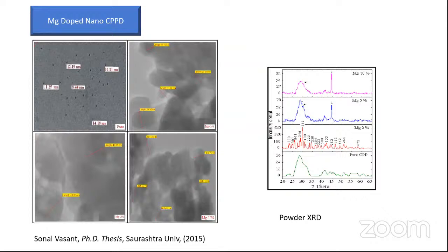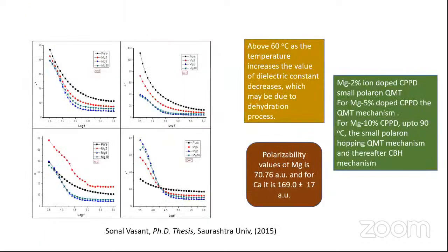These are the pictures of magnesium doped CPPD, and on the right-hand side, the powder X-ray diffractogram. And again, these show the variation of dielectric constant at different frequencies. For 2% magnesium ion doped CPPD, the small polaron and quantum mechanical tunneling mechanism. For 5% magnesium doped CPPD, the quantum mechanical tunneling mechanism. At 10% magnesium doped CPPD, the tunneling mechanism, and thereafter the CBH mechanism is developed. So they depend upon the concentration and also on the temperature. So this mechanism changes with different types of doping as well as temperature.